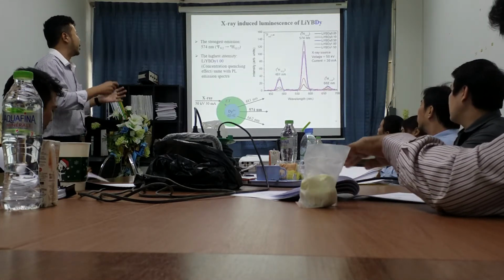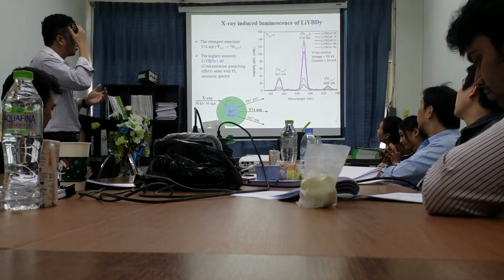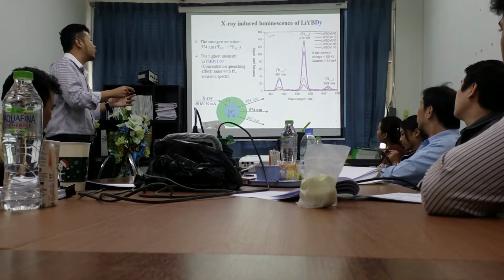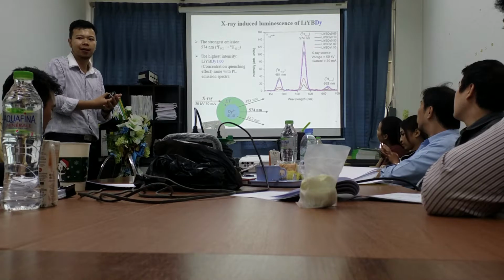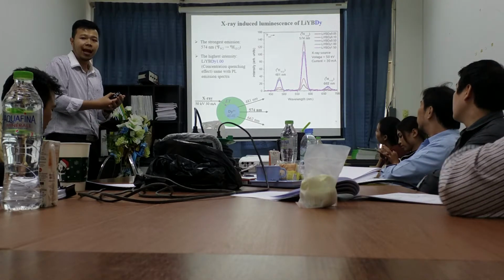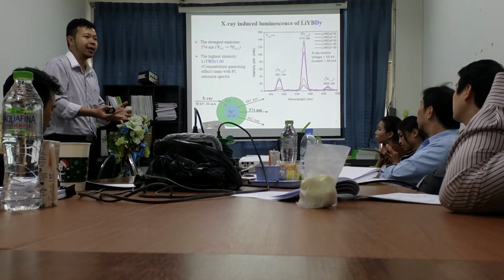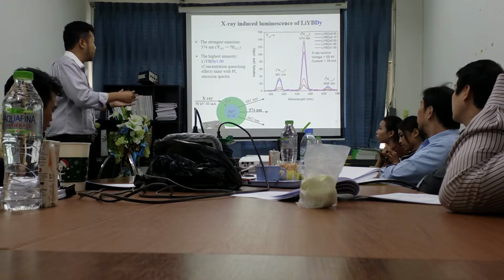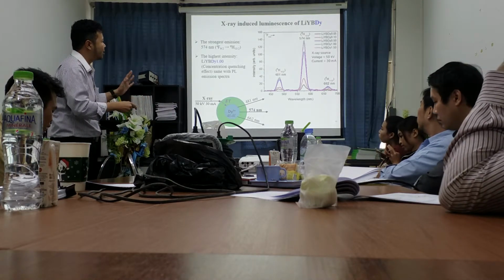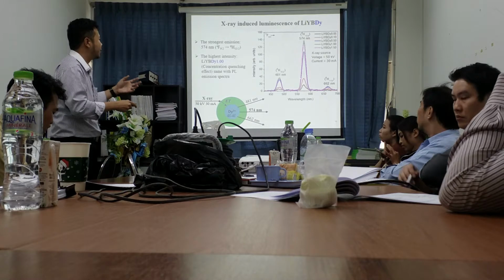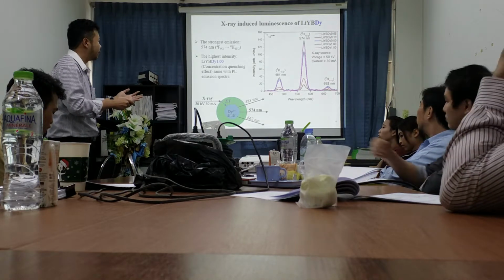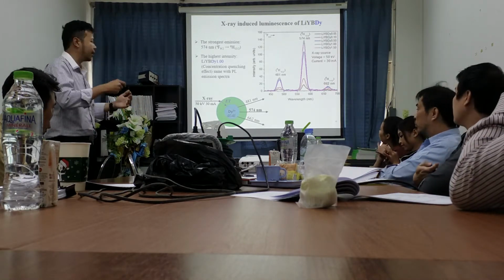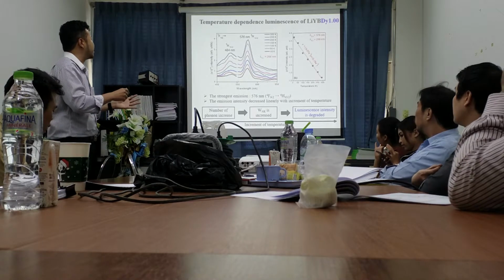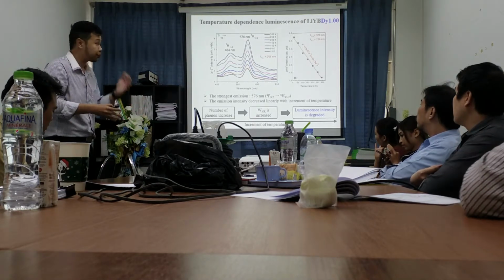Next, I move to the X-ray induced luminescence. We found that the X-ray induced luminescence shows the same spectrum pattern, similar to the photoluminescence that I presented to you before. Nothing changed, just a small shift of the peak, but the quenching and the pattern of the peak are the same. Next, this is the temperature-dependent luminescence.